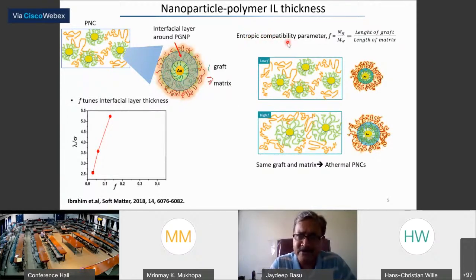So which is essentially driven by entropy, and then the entropic compatibility parameter is something which, for ease of understanding, one can define in terms of the graft molecular weight to the matrix molecular weight, or the size basically. And we had shown earlier that if you look at the interfacial thickness, that is the matrix and this graft chain, then that will scale with this parameter f. So that is something that we have as a tuning parameter, and this is something which can be varied independent of the thickness.